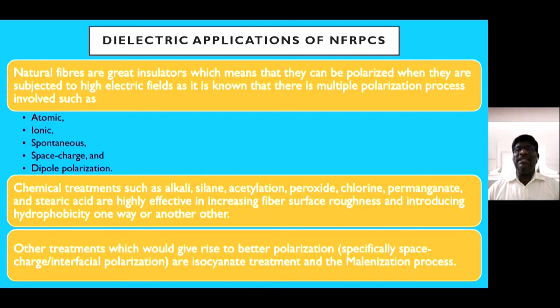Dielectric applications of natural fiber reinforced polymer composites. Natural fibers are great insulators, which means they can polarize when subjected to a high electric field. As you know, multiple polarization processes are involved. Any natural fiber has the property of an insulator, so they can easily polarize. When they can easily polarize, they can store charge. Different types of polarization take place: atomic, ionic, spontaneous, space charge, and dipole polarization. So when we apply an electric field on a natural fiber like acacia wood, it gets polarized so that it can store charges by means of these types of polarization.